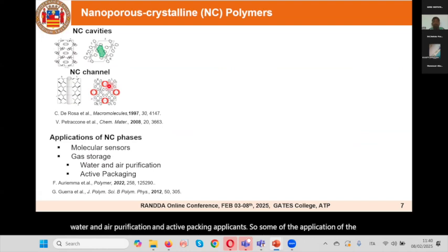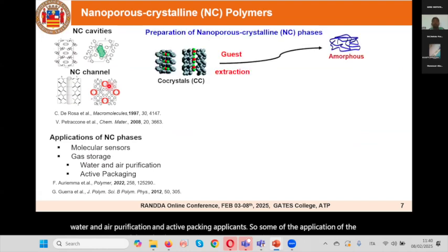Coming to the preparation, how to prepare the nanoporous material. We can prepare the nanoporous material starting from their co-crystalline phases. A co-crystalline phase is nothing but a complex between the long chain polymer and a small molecule, a small solvent molecule, called a co-crystal. From this co-crystal, by removing the guest molecule, guest extraction, they can form a nanoporous co-crystalline polymer. But it's a very rare phenomenon. Many of the co-crystalline pairs, by removing the guest molecule, become amorphous only.